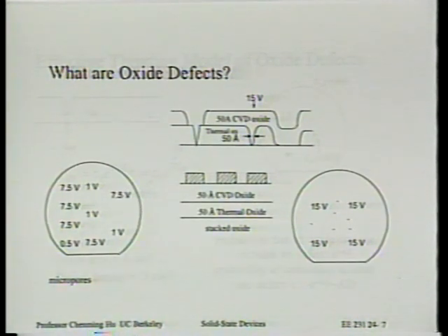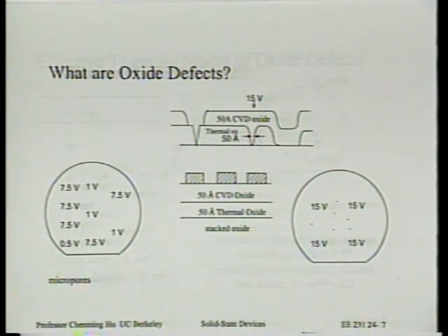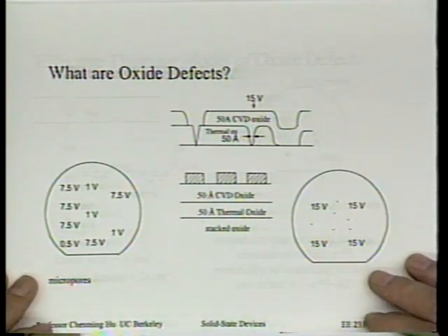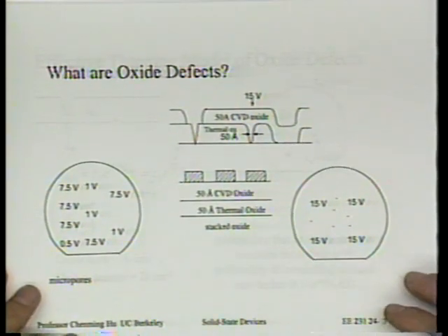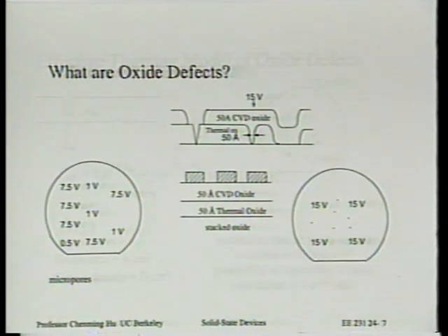It's very thin, less than 10 angstroms. Perhaps something like that. And maybe that tube exists as a result of some surface condition during the thermal oxidation, perhaps. And perhaps that can be fixed with the CVD oxide. So certainly this is pointing to that we should not be thinking about defects as just some very large piece of particulates. Perhaps something much more subtle than that. Okay, terrific.